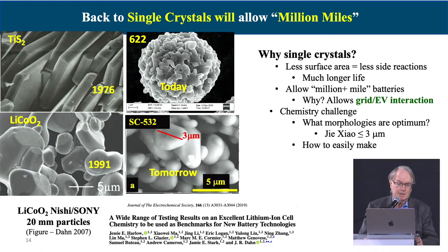So in the last two or three years, there's been quite a lot of work spearheaded by Jeff Dahn in Canada and by my ex-student Jianming Zheng at Pacific Northwest National Lab to go back to using single crystals. And I show you a picture of one there. So these single crystals have much less reactivity, which means they'll last much, much longer. And as Jeff likes to say, using the right nickel content, the right single crystal size, we can make these batteries last a million miles. I don't think any of us are going to drive a million miles. But what this means is you can connect your electric vehicle to the grid at all times when you're not actually driving it.